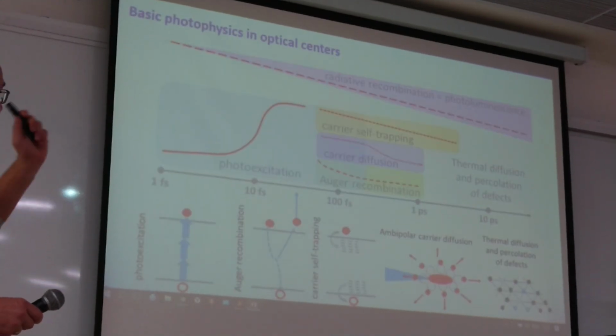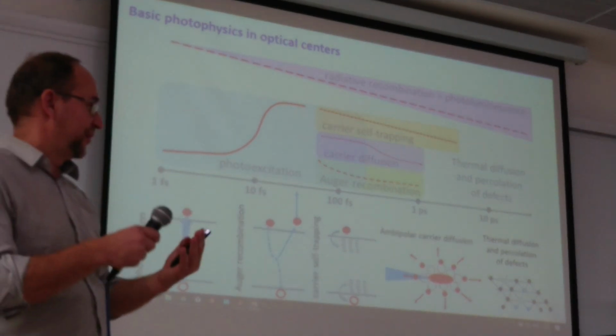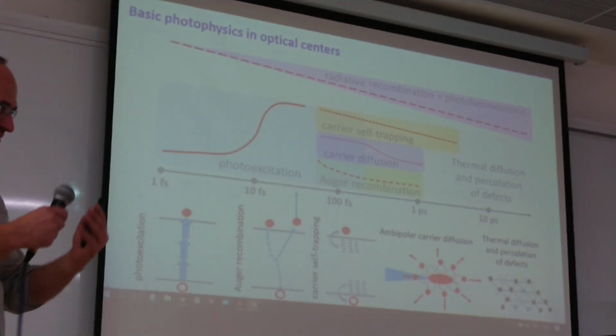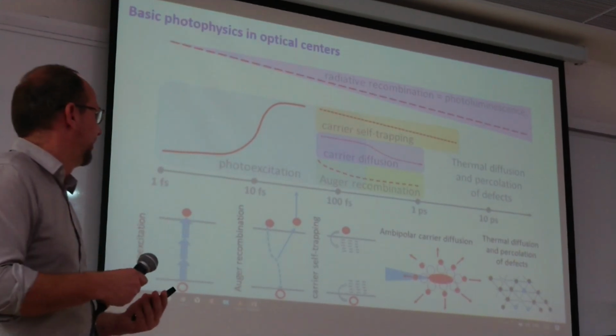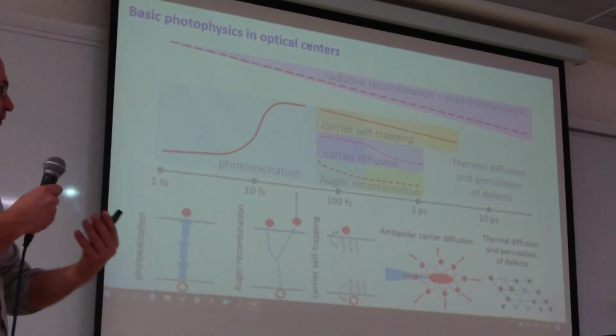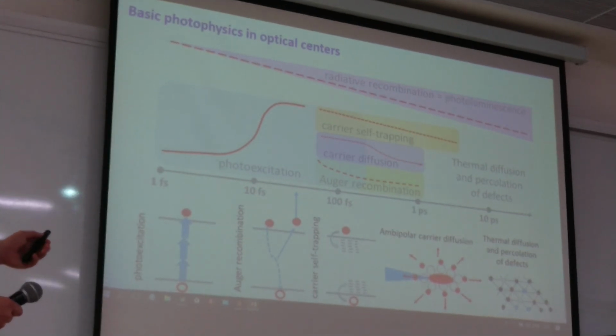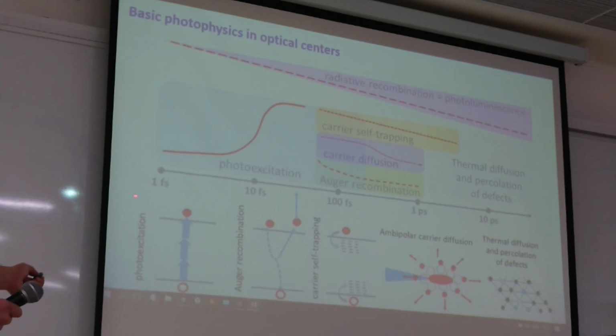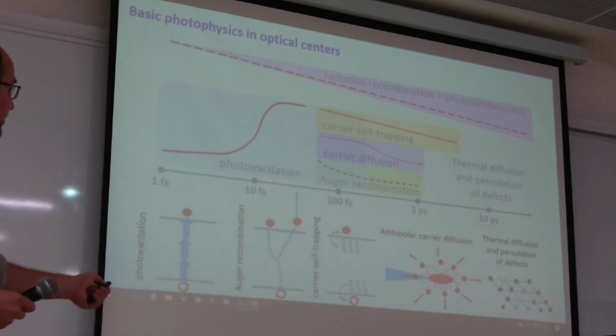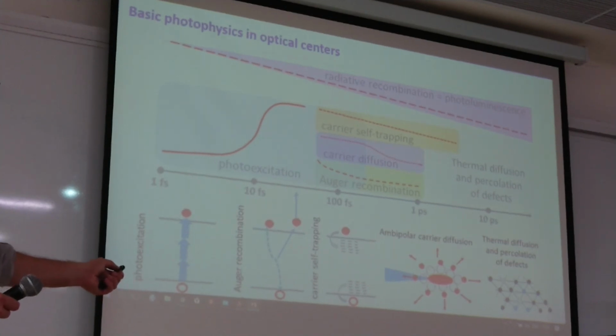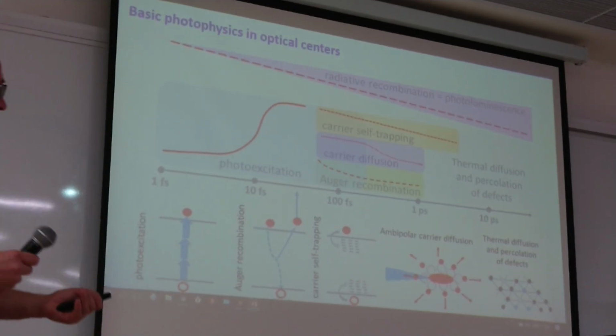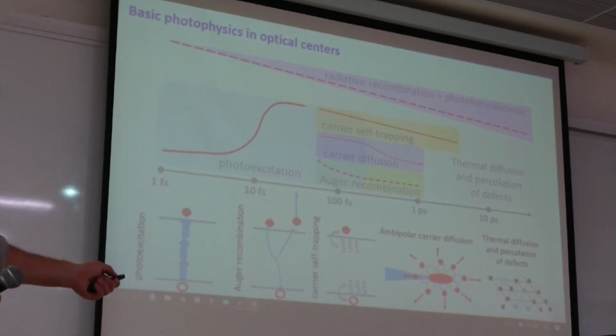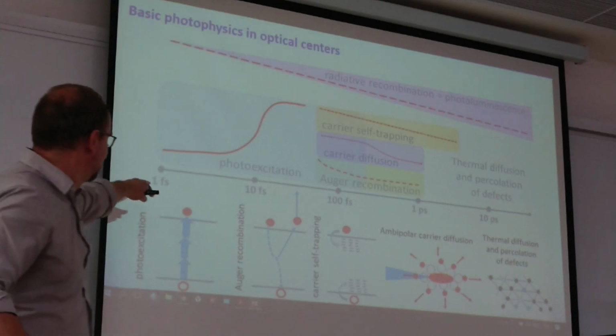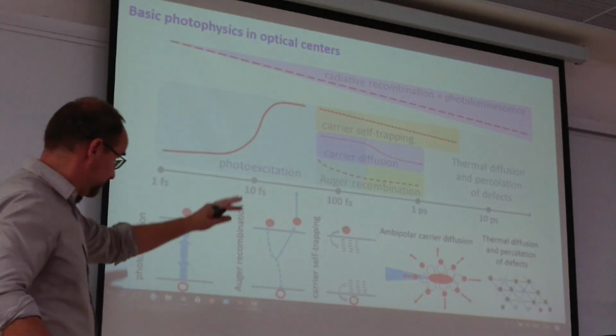But if you want to focus a femtosecond laser inside diamonds to produce this atomistic transformation of color centers, we are going through a whole set of different physical effects like photoexcitation by laser, then we produce plasma. These electron carriers can be recombined, can be diffused away, can be self-trapped by the lattice producing defects. Also there is a thermal step, diffusion or percolation, and this happens on a time scale from femtoseconds to multiple picoseconds.